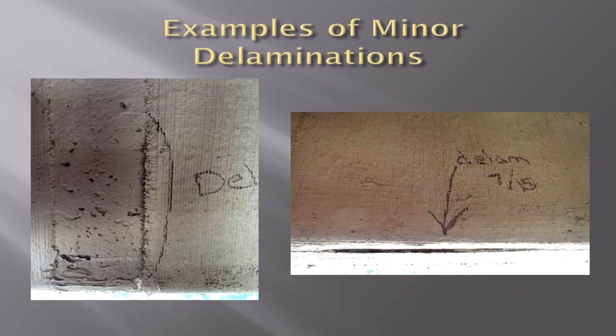Some examples of minor to moderate delaminations, and this could arguably be a major delamination since it's at the edge of an element. You can see from the picture here, and this is pretty common, I think, from the FRP that I've inspected, that the substrate probably wasn't prepared well. You see a lot of voids right on the edge of the carbon fiber wrap. So the putty, the primer, it didn't extend completely underneath the carbon fiber.